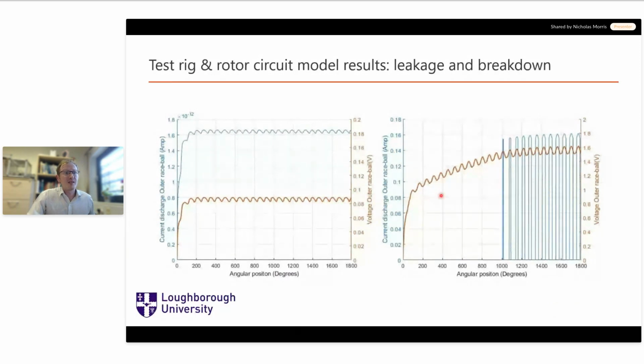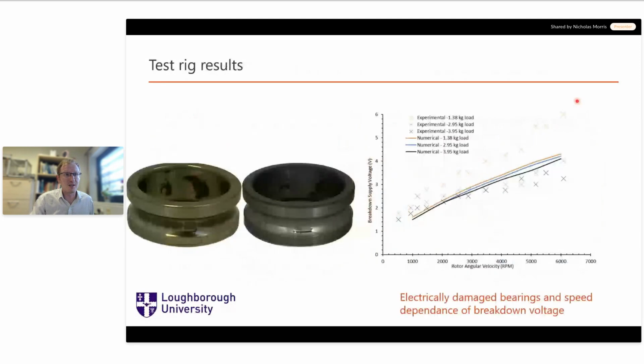When we reach a high enough field strength that we overcome the dielectric strength of the lubricant, then we create arcs, or in the model, it sees that as a low resistance contact. And we get these areas where we have a sudden discharge of electrical current. So you notice at the top here, there's no times 10 to the minus, this is just 0.18 amps. So we go from times 10 to the minus 12 to 0.18 amps. And so this current then is discharged between the surfaces. And it's in this condition, if I switch back to the previous slides, that we see these wear events taking place.